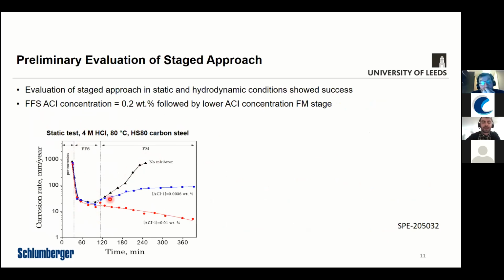And then depending on the amount of inhibitor used in the film maintenance stage and the second stage, varying degrees of protection could be achieved. So without inhibitor, it wasn't effective. There needed to be at least some inhibitor in there to maintain the film. And obviously increasing the concentration of inhibitor resulted in better performance from the staged approach.